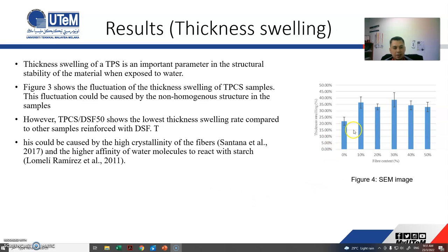Here we go for the thickness swelling. The thickness swelling results are increasing when the fiber content is increased. There is some fluctuation here, of course, which can be caused by the non-homogeneous structure in the samples. However, the 50% sample shows the lowest thickness swelling compared to the other samples. This could be caused by the high crystallinity of the fibers and the high affinity of the water molecules to react with starch. Basically, the starch is more prone to reactions with water as compared to the fiber.